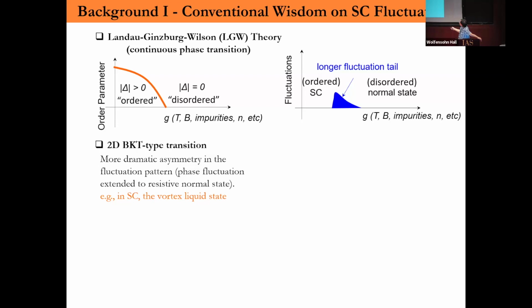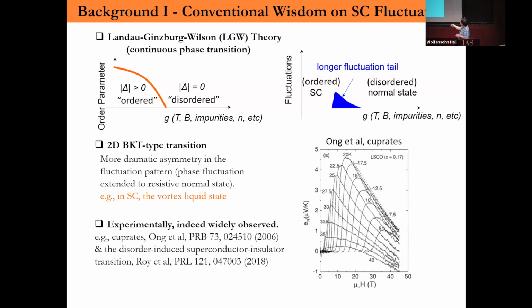And even though in this conventional picture we usually expect the fluctuation pattern to look like this on the disorder side - you have a longer tail of fluctuation because on the ordered side, the developed order phase really suppresses the fluctuation. So that's what you'd expect. And in the KT transition, you even have perhaps a broad liquid of the vortex signal. So you do have a very broad transition on the normal side. This is also experimentally observed, for example, in cuprates - you see there's a magnetic field induced transition, this is the shape. On the normal side, you have a fluctuation pattern that really penetrates into the normal state.